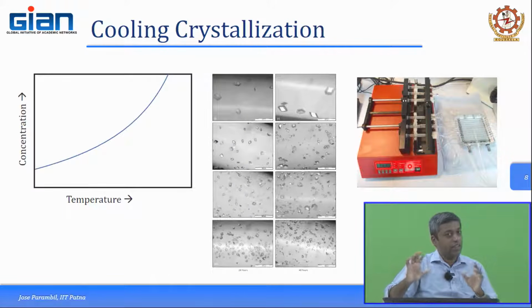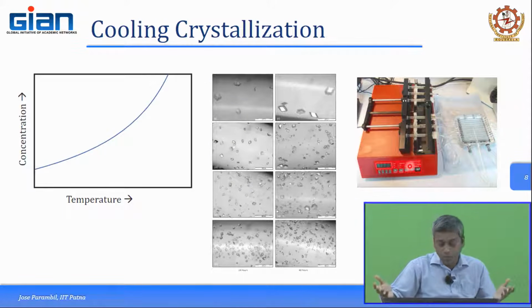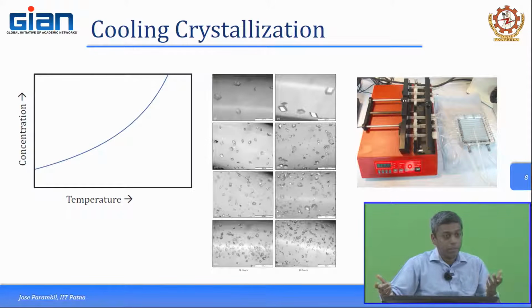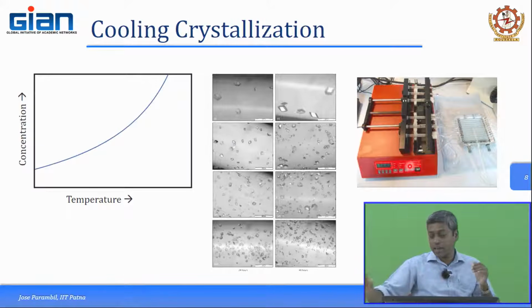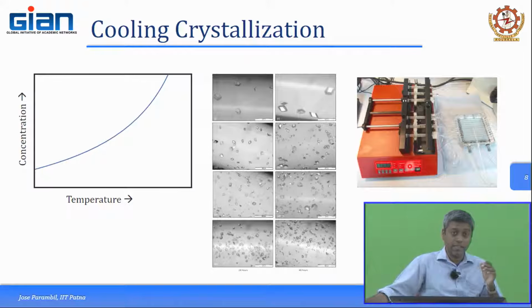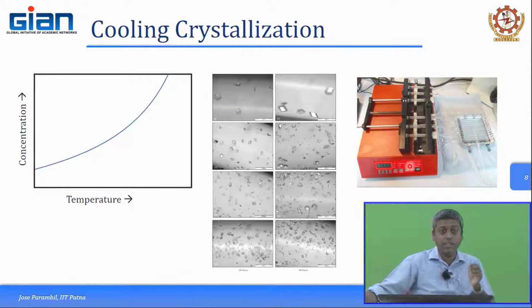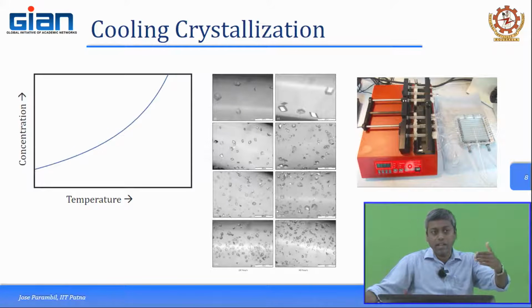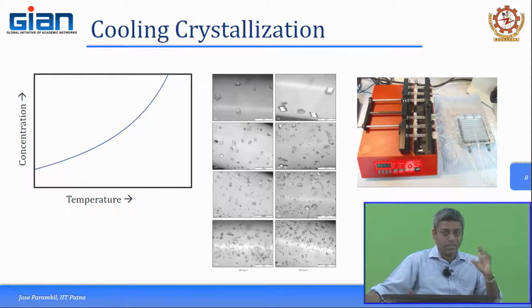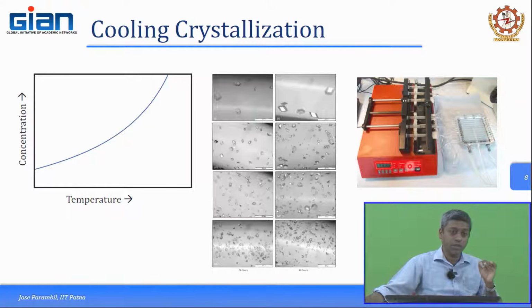So, even operation-wise, you are giving the same flow rate, but when you change the type of pump, the shear rate at which it is being pumped might affect your crystallization, and this is one of the major challenges with respect to protein crystallization. In some cases it might be good, because increasing the shear, to a level, might increase crystallization, but beyond that threshold it is trouble. So, there is a process optimization that you have to do in this sort of setup as well.